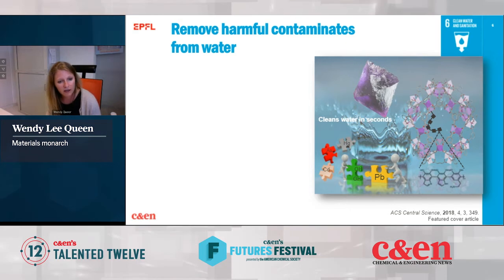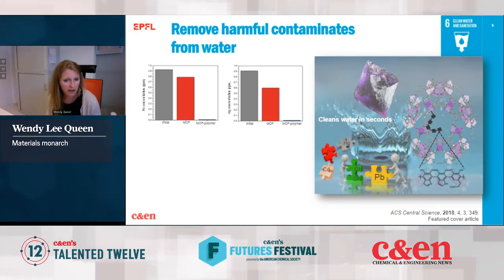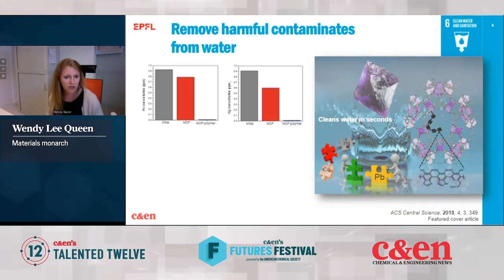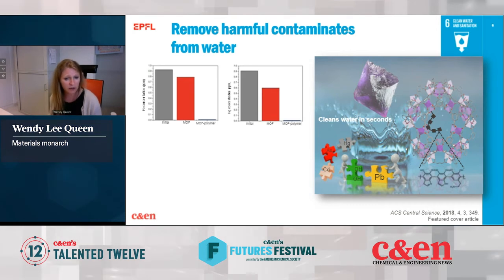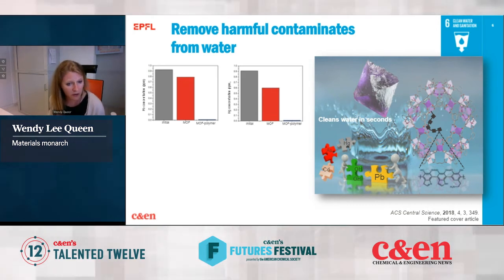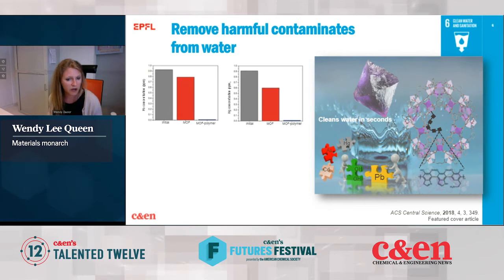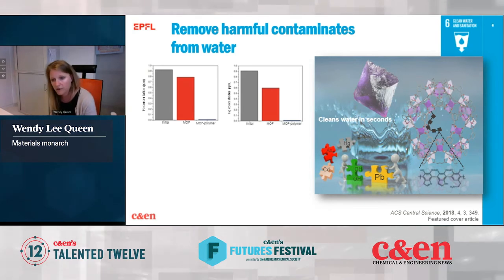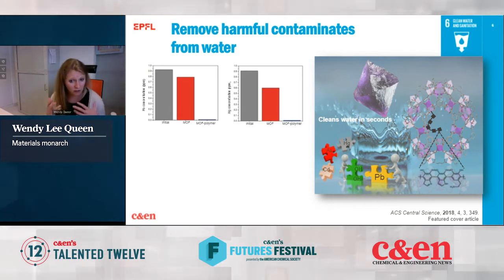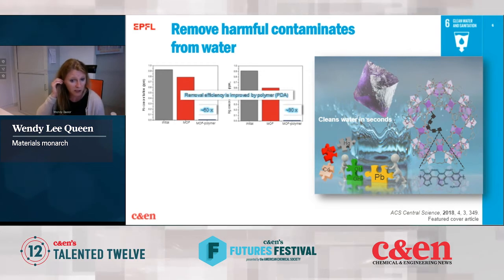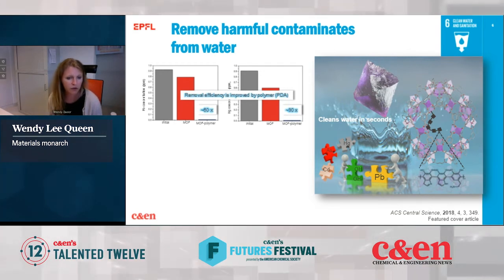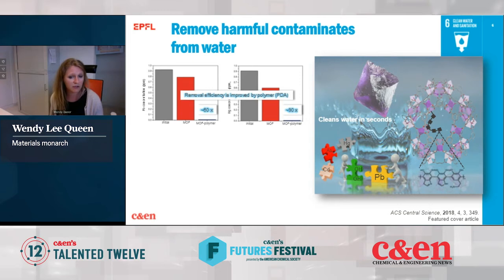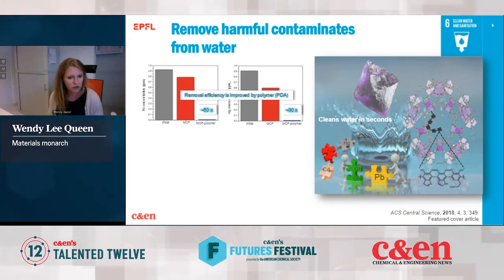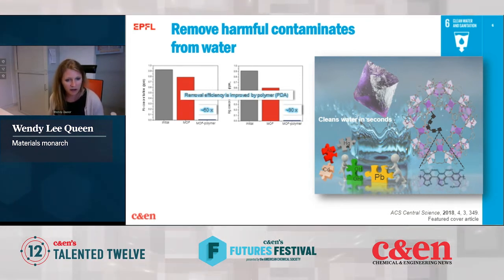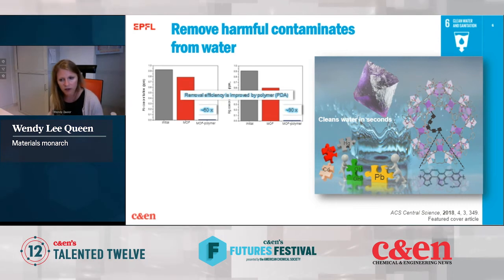You'll see lead on the left and mercury on the right. So in the gray, you'll see the initial concentration of lead and mercury. We've treated it with our metal organic framework. In red, you'll see the concentrations decrease a little. However, when we treat it with our composite, our MOF polymer composite, we see that the extraction efficiency is improved by factors of 60 and 90 times. So we get below drinkable levels and within a matter of seconds, and we can take up large quantities of